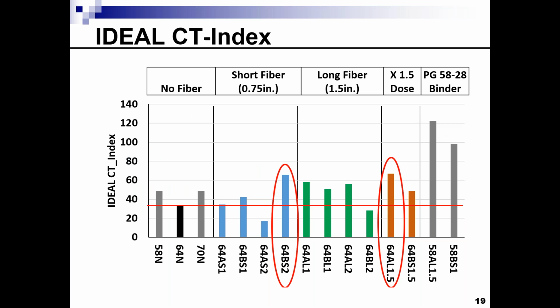We can see here that the short fiber B had improved the cracking, but according to the CTindex, you have to go to double the dose in order to get to the highest. One of the things that we considered in our recommendation is the cost. So although the improvement is higher, the cost might be higher too.